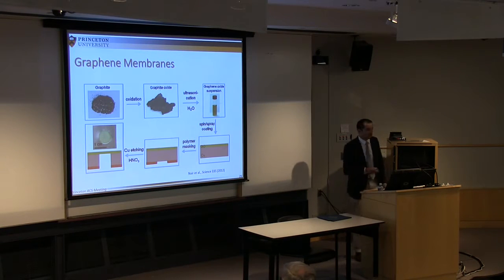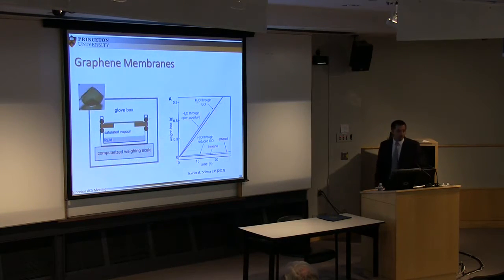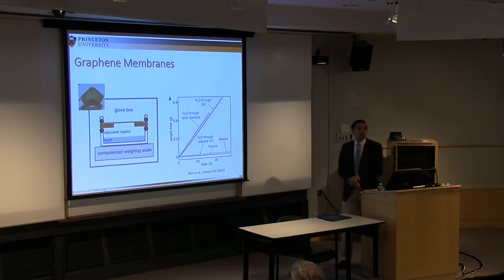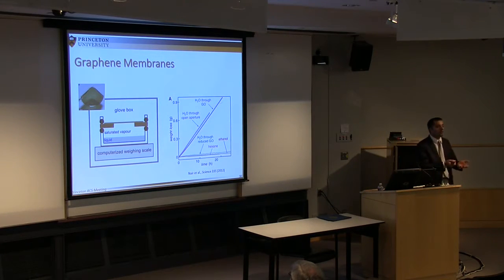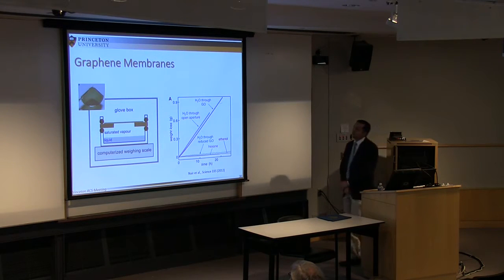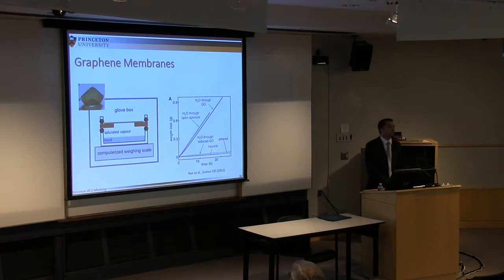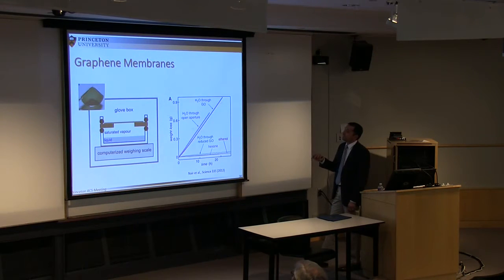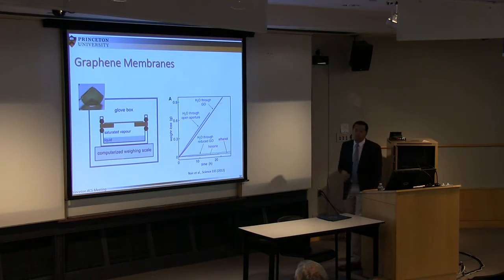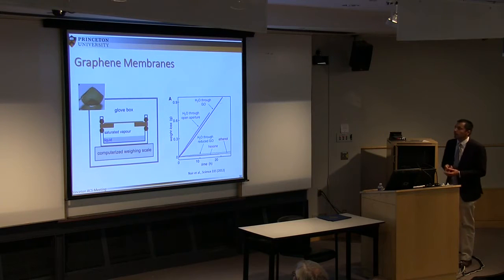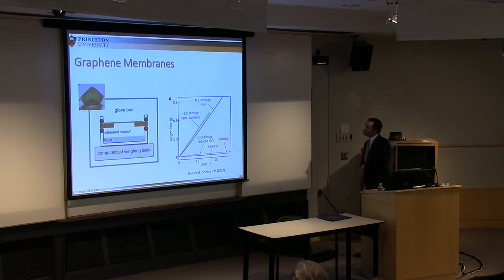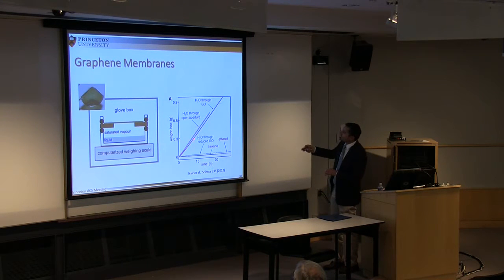So what you see in the center is a graphene membrane that will be tested. It looks like this, and it's collected through filtration. Very simple experiment: you have a suspension of graphene, you filter the solvent, and it forms a nice film like that, with thicknesses on the order of a few hundred nanometers up to a few microns. So in the first experiment, they tested a liquid, water, and other solvents. What they do here is record the rate of evaporation of the solvent through the graphene membrane. And interestingly, what you see here is the control experiment.